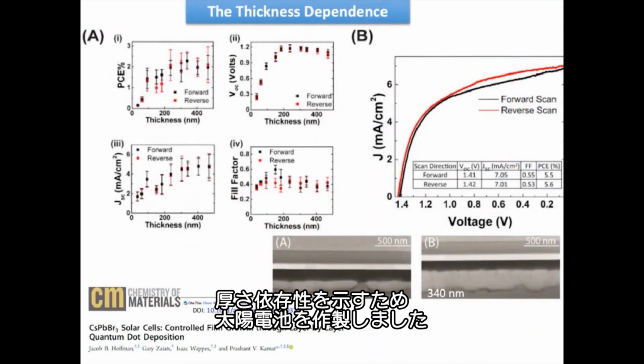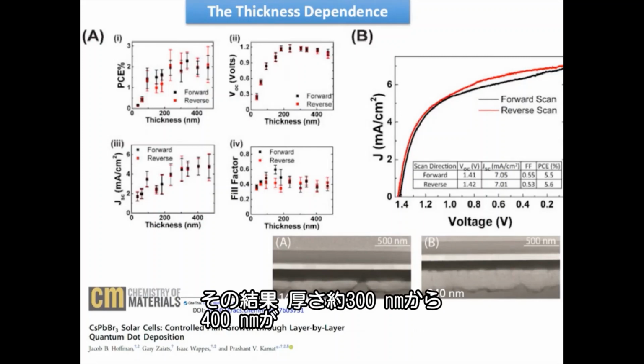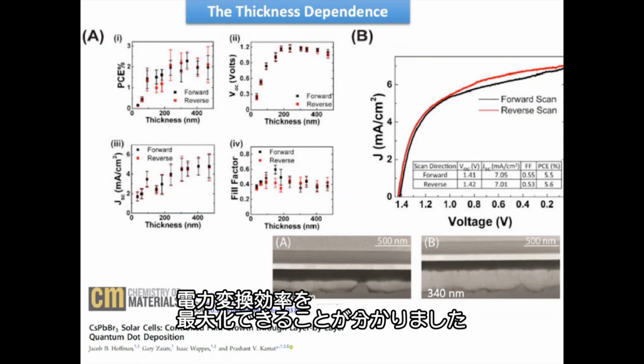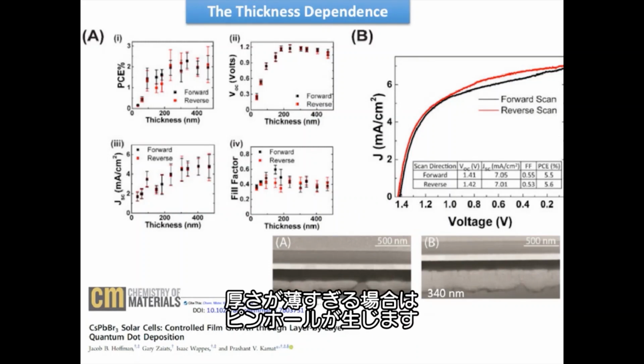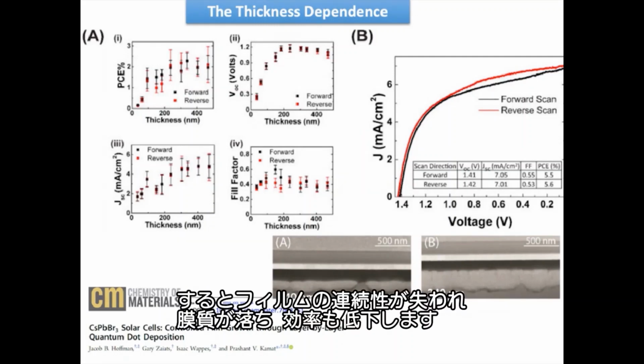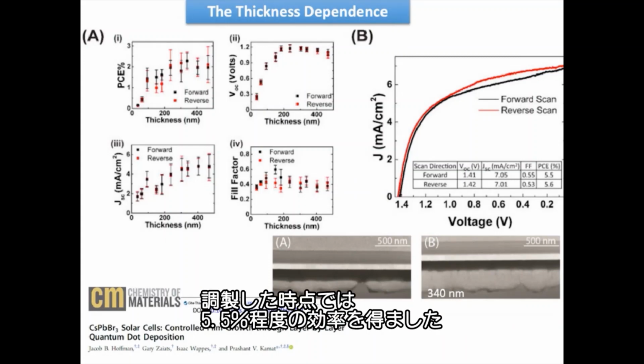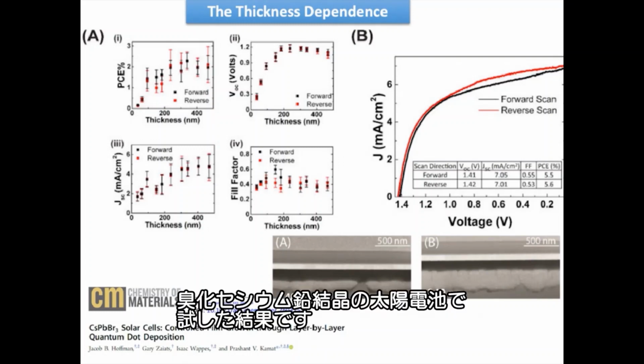We have made solar cells to show the thickness dependence, and we find that about 300 to 400 nanometers is an optimal thickness to get the maximum power conversion efficiency. If the thickness is too small, then you get a lot of pinholes. As a result, the film is not continuous, the quality of the film is poor, and so we get poor efficiency. In this case, at that time, we got about 5.5% efficiency with these solar cells prepared with the cesium lead bromide crystals.